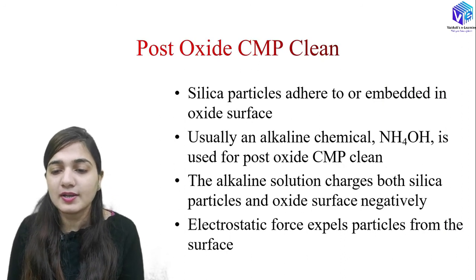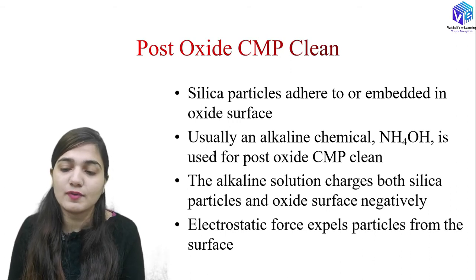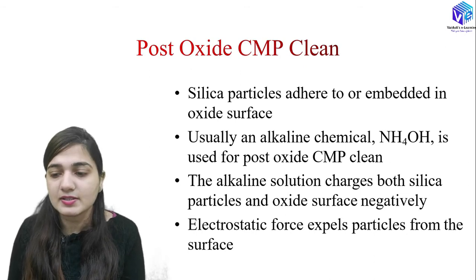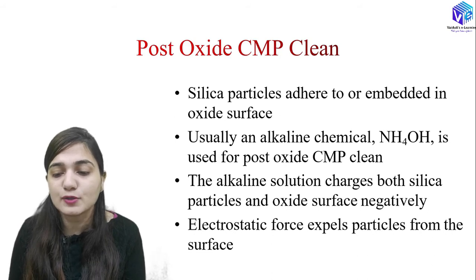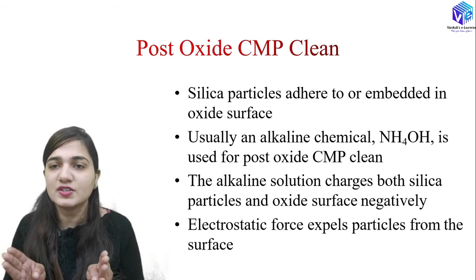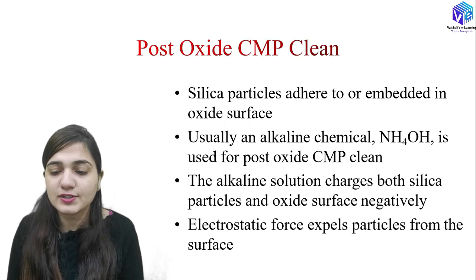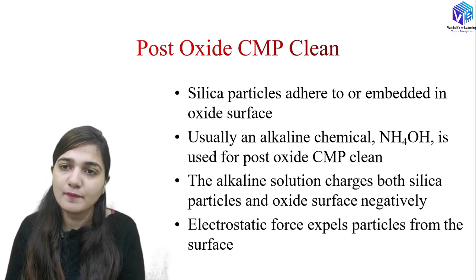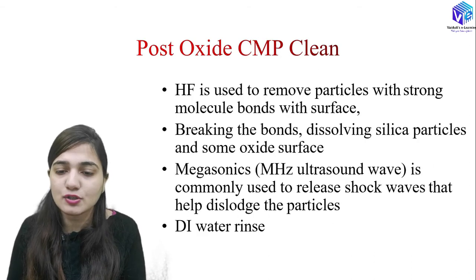Coming to the silica particles: silica particles adhere or embed inside the oxide surface. We can use alkaline chemicals to remove the silica particles, and NH4OH is commonly used for post oxide CMP cleaning of silica particles. The alkaline solution charges both silica particles as well as the oxide surface negatively. So when both are negatively charged, they apply a repulsive force on each other and the electrostatic force expels the particle from the surface.